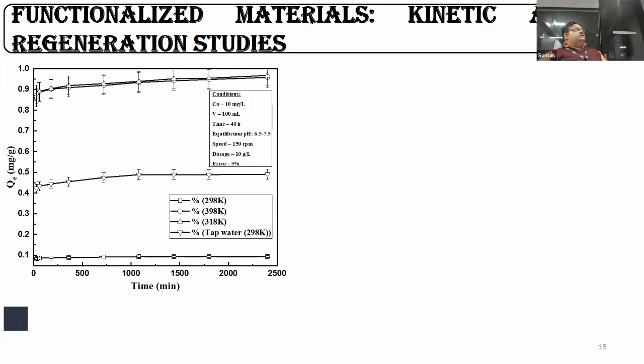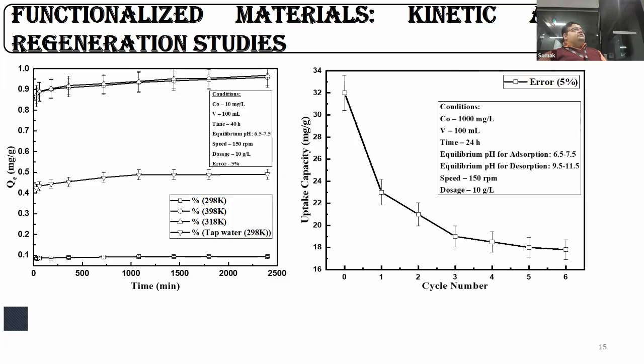It starts from 1000 minutes until the point where saturation starts taking place. Coming on to the regeneration study, after the third and sixth cycle, some of the active sites are permanently lost, and when they are permanently lost, the uptake capacity decreases heavily and they are not able to recover. But still, after the sixth cycle, the uptake capacity for the exhausted bead is still 18 milligram per gram, which is comparatively higher than some of the conventional adsorbents.